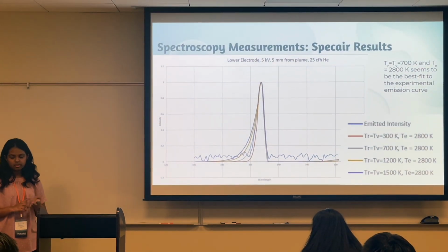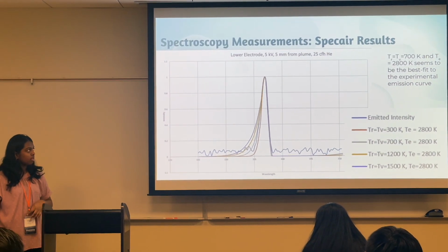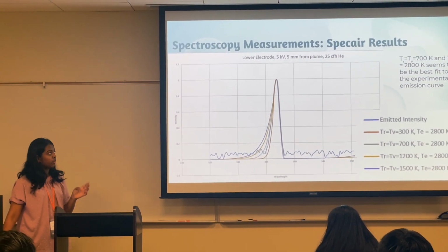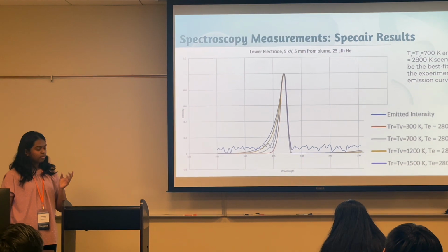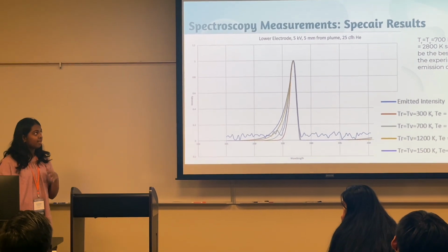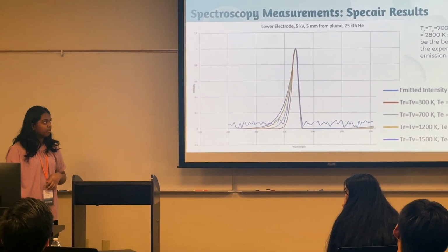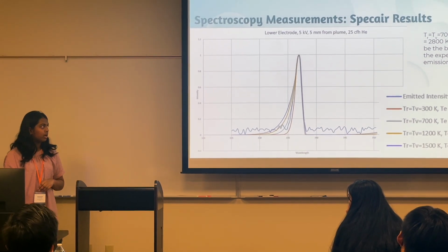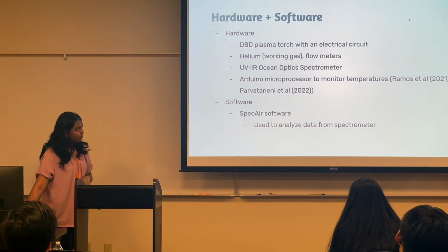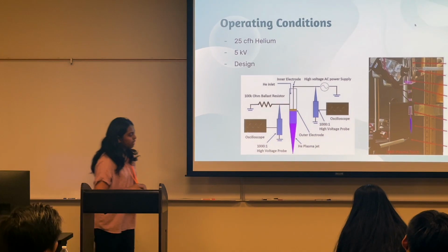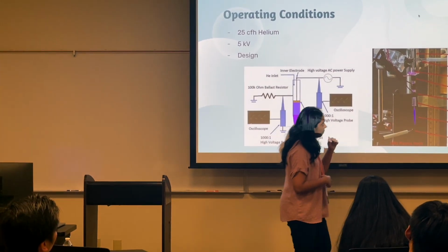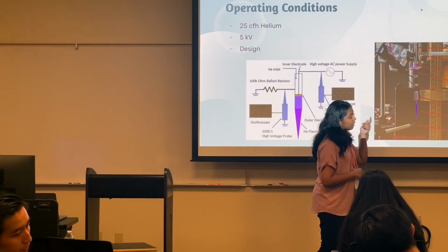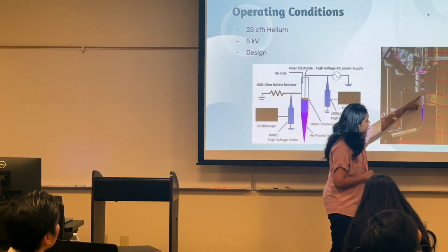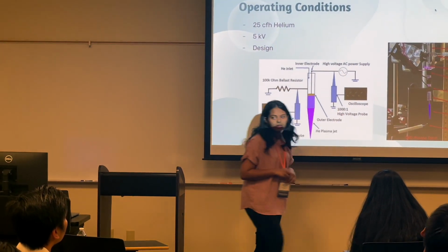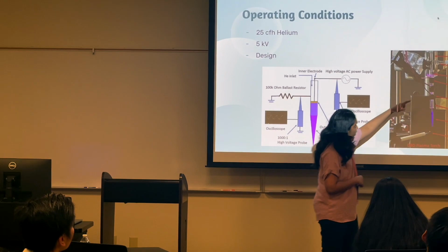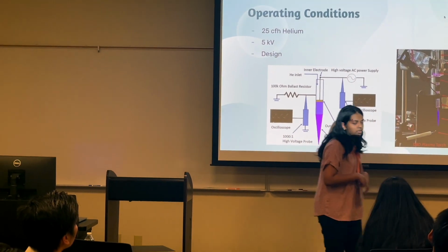So I'm going to show you 4 different conditions. This one is the lower electrode, 5 kilovolts, 5 millimeters from the plasma jet exit, and 25 cubic feet per hour of helium inputted. So what that means is that, for example, over here, we're connecting the voltage into the lower electrode to generate the plasma. And if I said upper electrode, that would be like over here in the upper electrode.